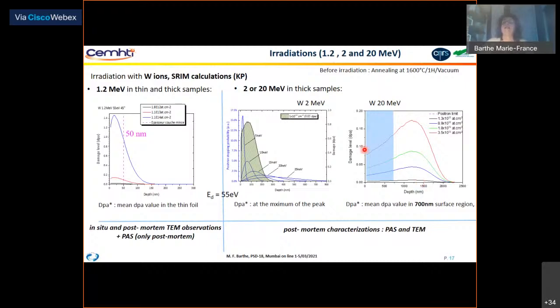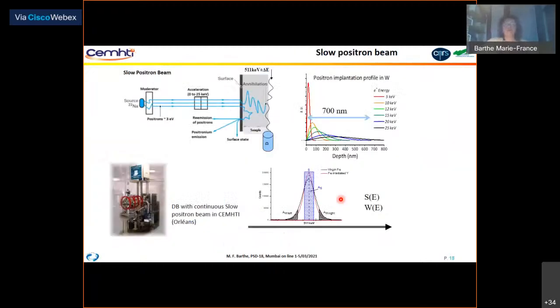And for 20 MeV, the maximum of damage is reached at about 1.34 micron. And it is interesting to see that in this region, we have not too much change in the dpa level. And this region corresponds to the region that can be probed by slow positrons, so the first 700 nanometer. So we are able to perform TEM observations and PAS in these thin samples or thick samples. Okay, so just to remember that slow positron, we do the slow positron in CEMHTI, and as I said, it allows to probe the first 700 nanometer under the surface in tungsten as a function of depth